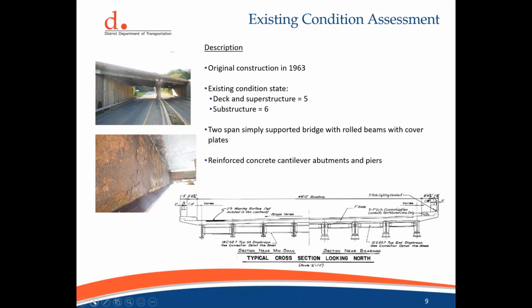The concrete abutments and piers were of the conventional type of construction for the day, consisting of joints over top of them. And being in Washington, D.C., the area is prone to snow, and so de-icing salts get in there, and when the joints wear out, the de-icing salts get down in and they start to corrode, lock up the bearings, and begin to destroy the end of the girders. You could see the photo on the left of the screen. That's one of the girders, not near one of the bearings, but you could see the deterioration of the girder flaking off of rust.